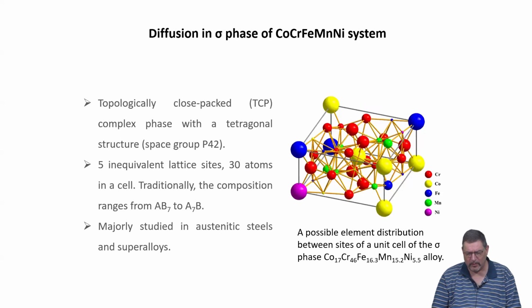Now, diffusion in the sigma phase. The sigma phase is displayed here, and you can see it's quite a complex phase. So it is astonishing, I think, that you can have 5 elements finding their sites. It's certainly a completely different way a high entropy material is designed, because here you have certain sites which are assigned by nature for some of the elements, and other sites which are then assigned for again the rest of the elements. So you see there are 5 inequivalent lattice sites.